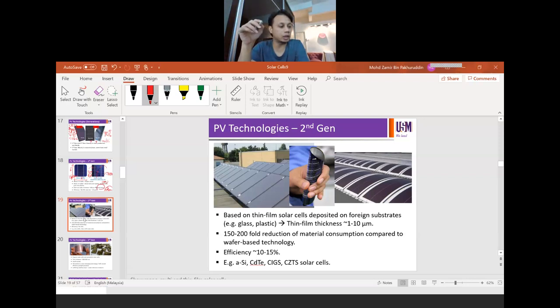Waktu saya buat PhD hari tu, when I did it in UNSW, I worked on second generation solar cells, which are based on polycrystalline silicon thin film on glass. So back then I worked on this. So ada glass kat sini, glass. Then I have my polycrystalline silicon. So the thickness is only about 10 micron. Okay. And the polycrystalline silicon was originally deposited by electron beam evaporation process.